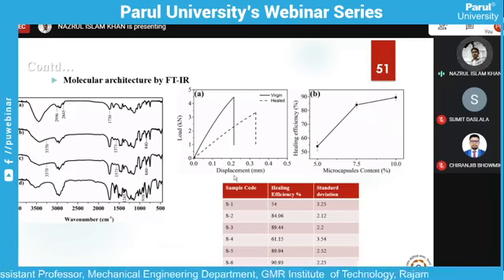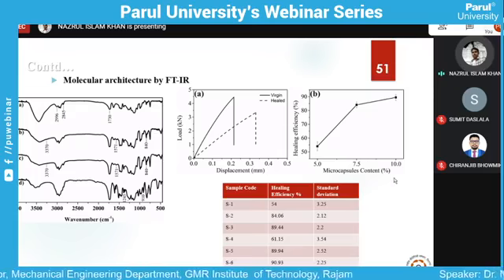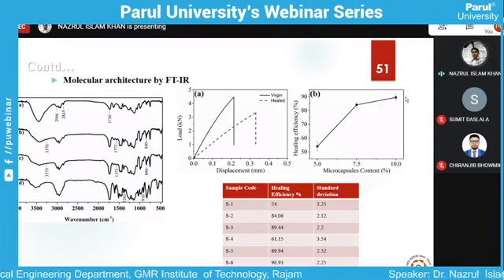We got a healing efficiency of near about 90%. What was the microcapsule content? At 10 weight percentage of resin and hardener, we got 90% healing out of the material.